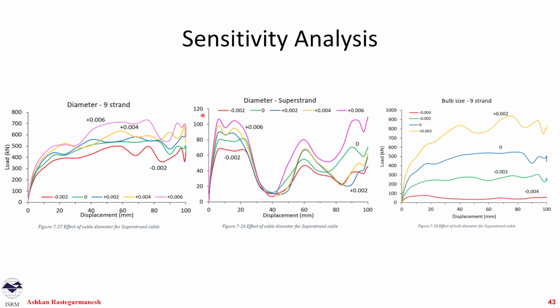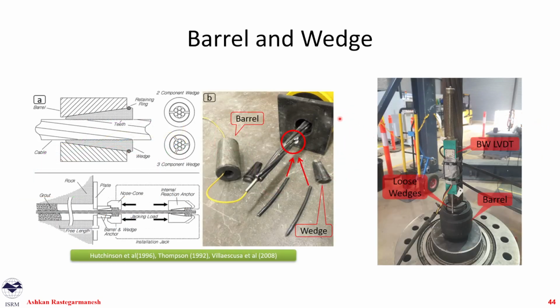The other three sensitivity analyses were on the diameter of the cables, the diameters of the bulb cables, plain cable, and the change in diameter of the bulb. As we can see, the change in the diameter has a major effect. However, the most interesting thing is the change of the bulb. So even a 2 millimeter change in the bulb, making it smaller or larger, can have a significant effect on the load value. It's very easy to see that even a 2 millimeter increase in bulb diameter gives us almost twice the load, or the opposite in the other direction.